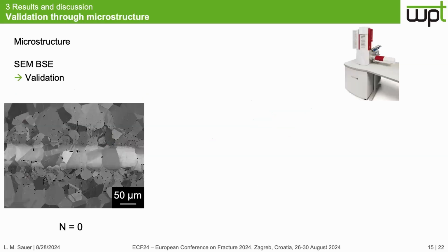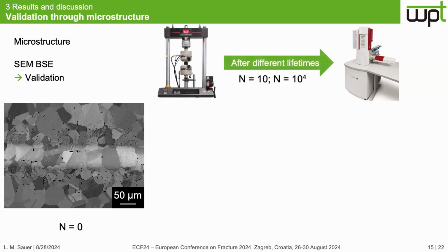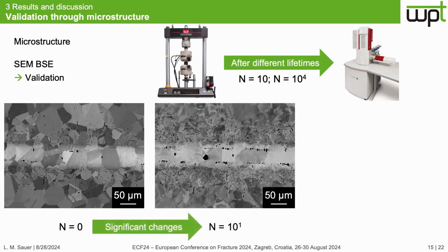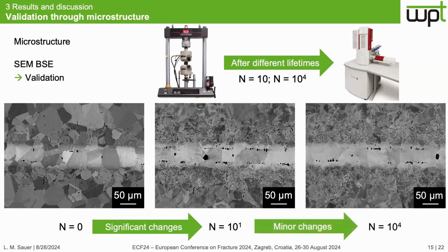And to validate this result, the microstructure of the specimen was analyzed by using a scanning electron microscope and the BSE contrast. And the microstructure of the initial state was compared with the microstructure after different lifetimes, in this case after 10 cycles and 10,000 cycles. From the initial state to the microstructure after 10 cycles, there's a significant change. But from 10 cycles to 10,000 cycles, there are only minor changes in the microstructure. And this fits with the previously shown results.